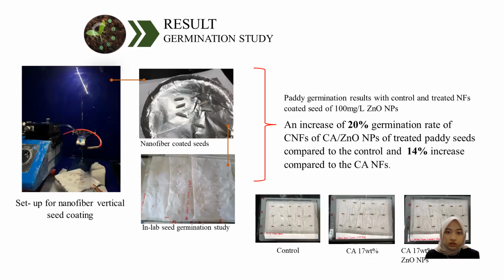Eventually, this is the result for the germination study. We can see here an increase of 20% in germination rate for the zinc oxide inclusion with the cellulose acetate compared to the control, and also a 14% increase compared to cellulose nanofiber alone.